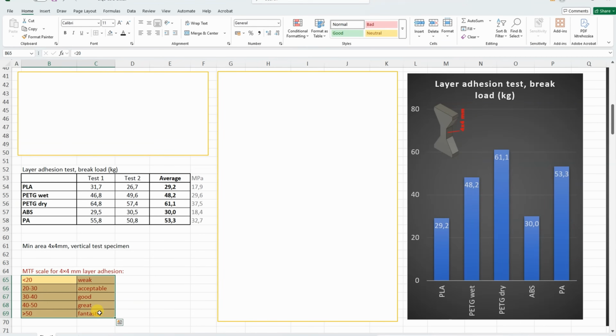This is my rating for this size of the test object, and again a little bit lower numbers for the PLA and ABS, but these are still acceptable too. And look at this fantastic layer adhesion for the PETG, and for the layer adhesion it is very important to dry the filament. And the PA also has fantastic layer adhesion.